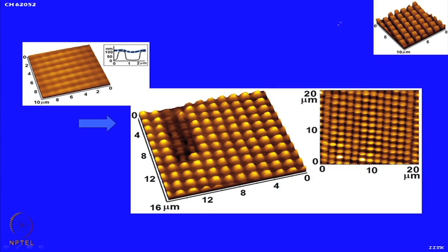In contrast, even on this template with this 2D order, this array of square pillars, if you now have a focal adhesion where the film is just touching only the top of the asperities or the top of the protrusions, you can again see that the droplets now go and align themselves on top of the pillars. This is a nice image. I like this image a lot because it had a zone where it had some defect.